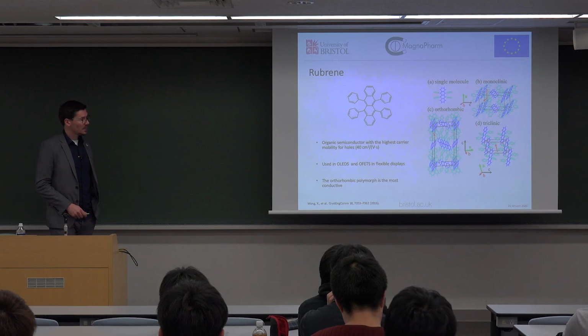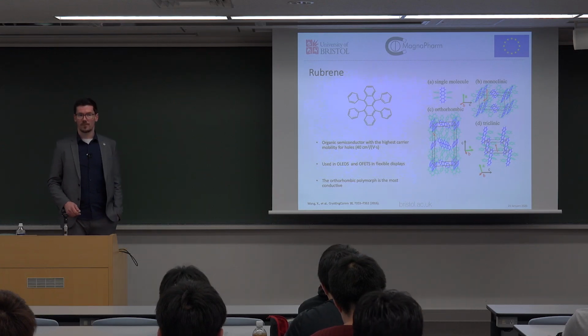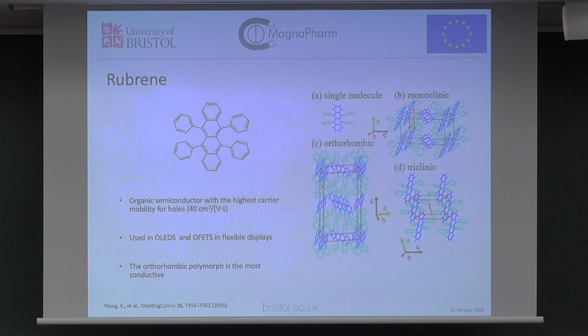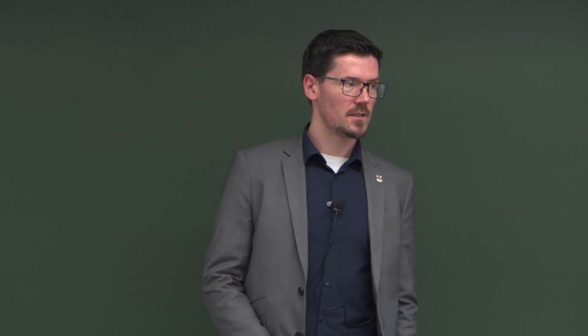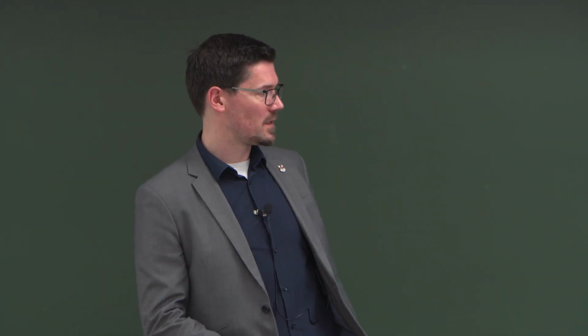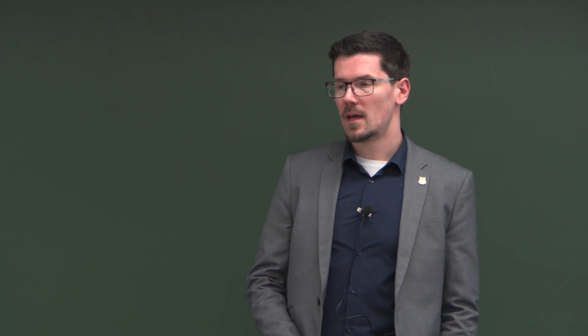Rubrene, a molecular crystal, as far as I'm aware, still has the highest conductivity of any molecular semiconductor. It's used in OLEDs and OFETs, but there are a number of different polymorphs. The orthorhombic form is the most conductive. So luckily, if you're growing rubrene to build devices on semiconductors and whatnot, chances are you'll end up with the orthorhombic form, which is the most thermodynamically stable.